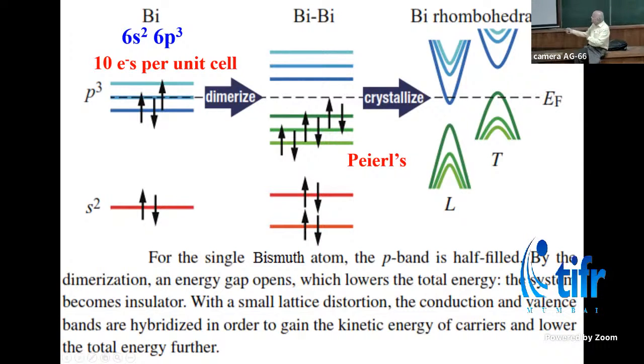So let us try to understand from the chemistry. You have 6s2, 6p3 outer electrons in bismuth. Ideally, it should dimerize and become an insulator with a cubic structure. But here the Peierls distortion strikes in. It so happened that energetically it is good to make this rhombohedral distorted lattice, which gains in energy and gives you a very funny band structure. If you look at the L point, the bottom of the conduction band is much lower than even the top of the valence band. This is the crucial thing about bismuth. It has a very funny structure.